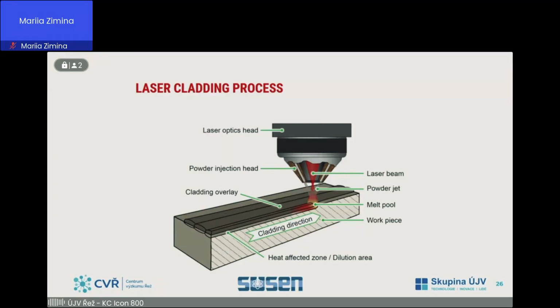And weld dilution is substantially reduced over conventional welding methods, resulting in a much smaller heat-affected region. The potential cost savings from this technology is substantial, assuming that the thickness of cladding can be reduced by over 1/2 compared to conventional cladding methods. For the NuScale power reactor, which is clad over both the inner and outer surfaces, the amount of cladding surface area is projected at almost the surface area of 2 Olympic-sized swimming pools.